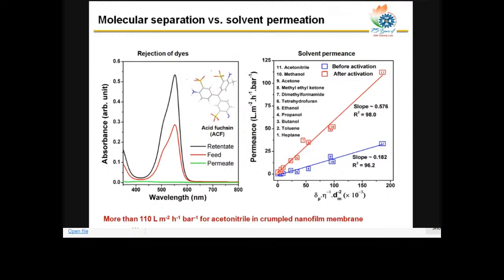So in a collective way, if we plot the solvent parameter against the permeance of the solvent, we get a straight line behavior. If we fit this with the model equation, we can calculate the solvent permeance of any unknown solvents from these two straight line behaviors.